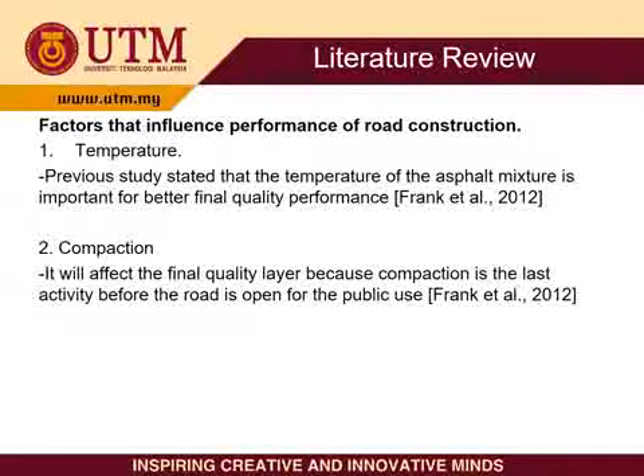And viscosity of the asphalt mixture is influenced by the different techniques for WMA, but on the other hand, the viscosity will increase again when the temperature of the mixture is lower. In order to obtain high density, optimal compaction should be reached.